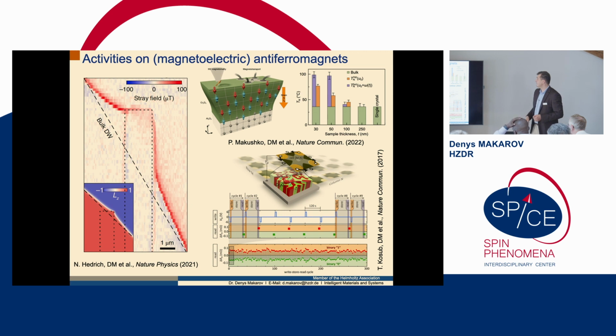We work also on magnetoelectric antiferromagnets. And again, as you can see, in our case, it's chromium oxide, a collinear antiferromagnet. What is important there is if you create some kind of obstacles, you just simply pattern your sample, you will have a chance to pin domain walls, antiferromagnetic domain walls. And now you can investigate, in this case with NV microscopy measurements, how antiferromagnetic domain walls in collinear antiferromagnets interplay with boundaries. And this appears to be also very, very exciting and fundamentally very new, right?